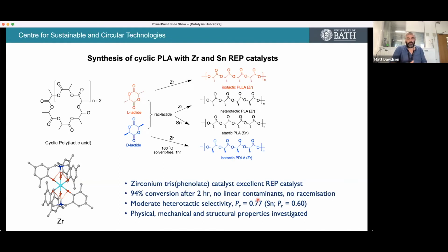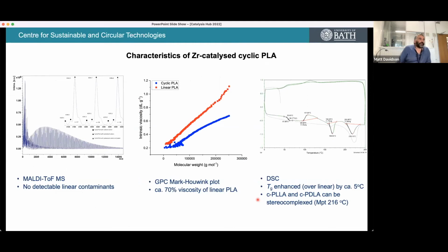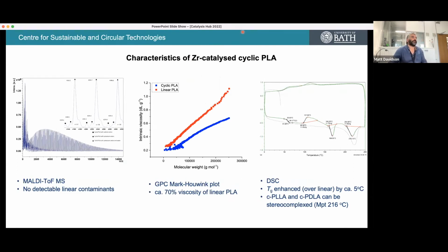So with this well-controlled polymerization to give us cyclic compounds in hand, we thought we'd better do a little bit of further investigation of these things. So just some of the data that characterizes the cyclic PLA that we're making here. This is MALDI-TOF mass spec. You can see from this, all of these species here are cyclic species. There's no linear contaminants that we can see by mass spec.